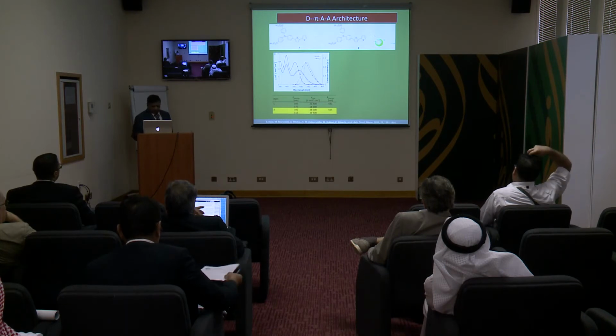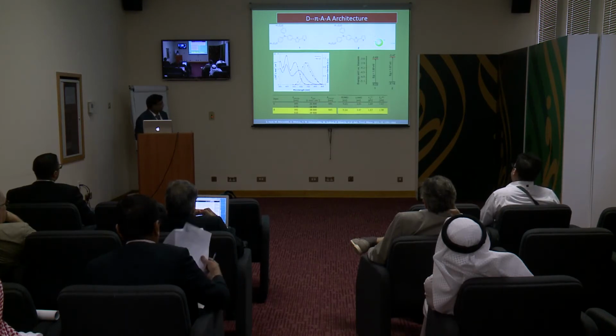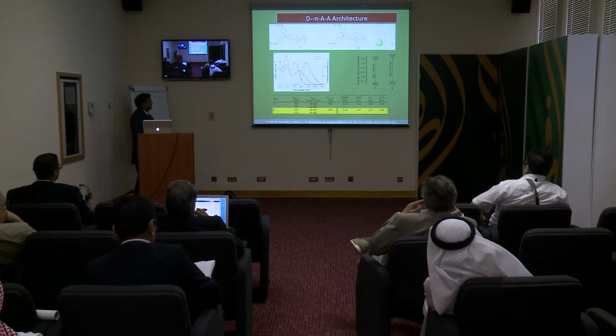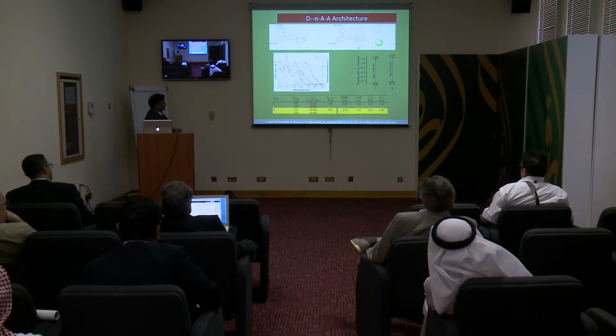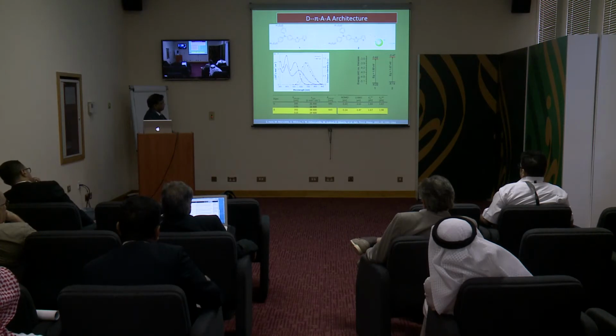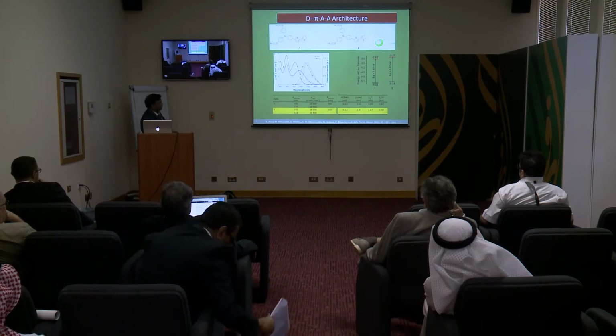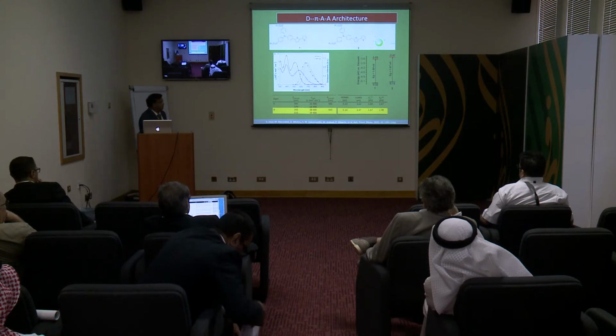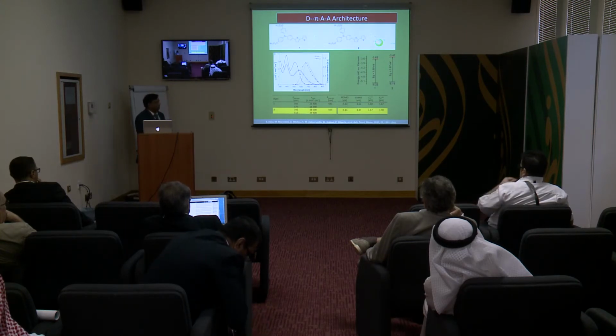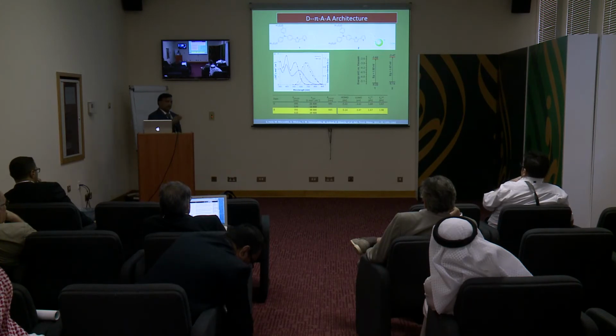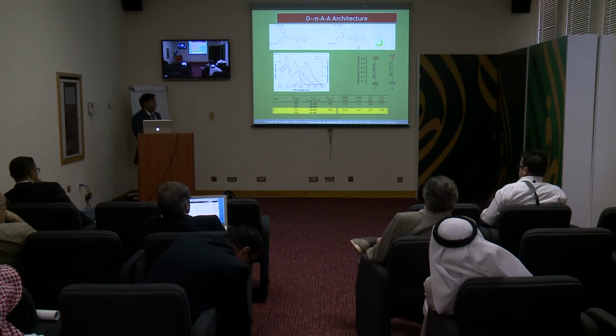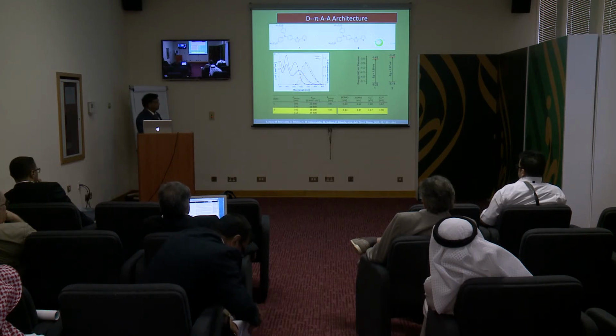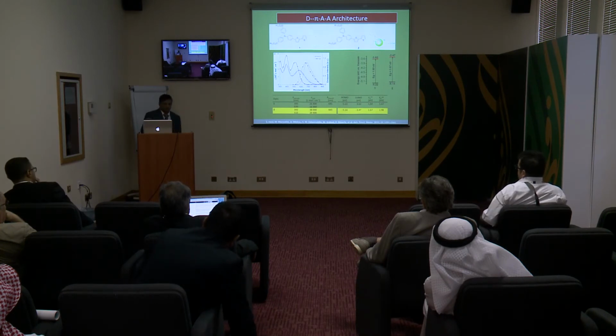If you look at the spectral properties, this is the molecule which has a benzothiazole attached directly to the carboxyl group. But by having a phenyl group in between these two, it blue shifts the spectral response. In fact, that's not what we want, but by having a phenyl group in between the acceptor and the anchoring group, it blue shifts the spectral response, and then you expect that this molecule should give you the highest performance when compared to this molecule, because the spectral response is blue.